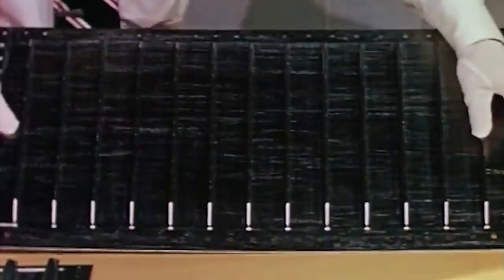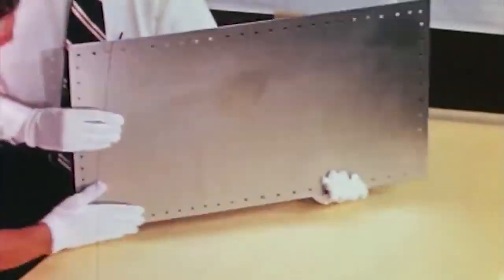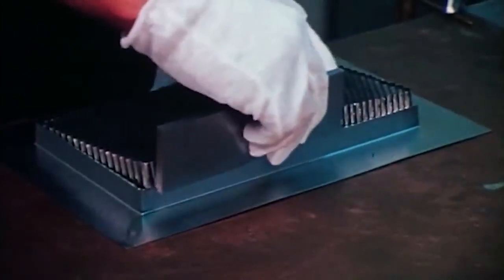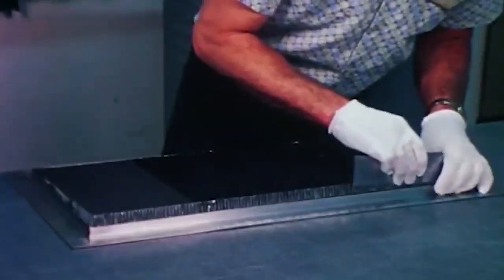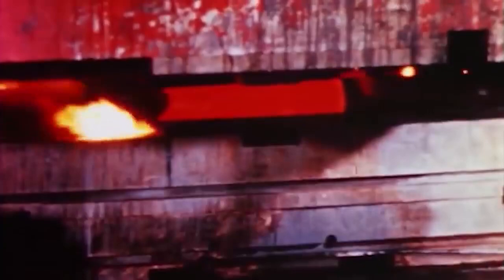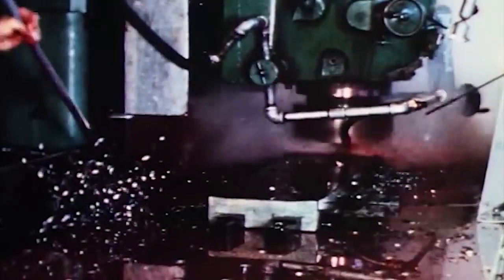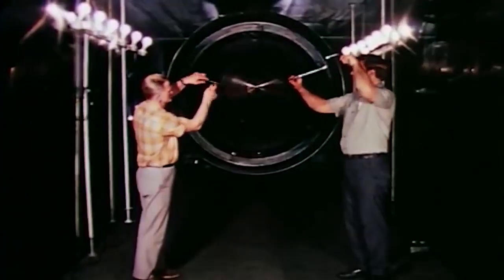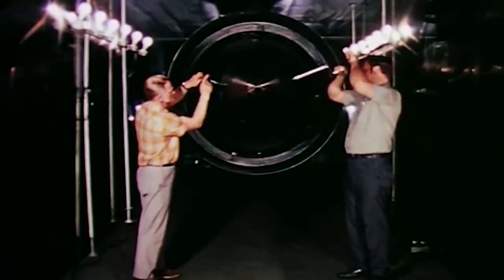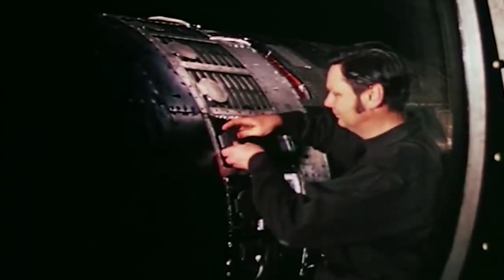This process results in an incredibly expensive material that becomes even more expensive as a result of the difficulty the engineers found when attempting to form it into its final shape. The engineers of the SR-71 were among the first people in history to make real use of the material. In that process, they ended up throwing away a lot of material, some through necessity, some through error. At times, the engineers were perplexed as to what was causing problems, but thankfully, they documented and catalogued everything, which helped find trends in their failures.